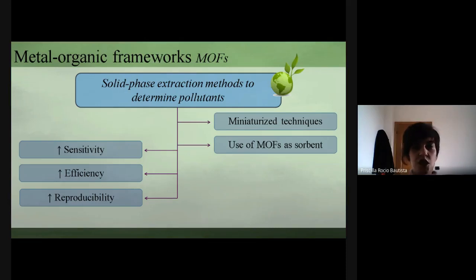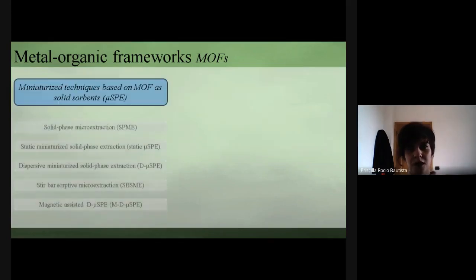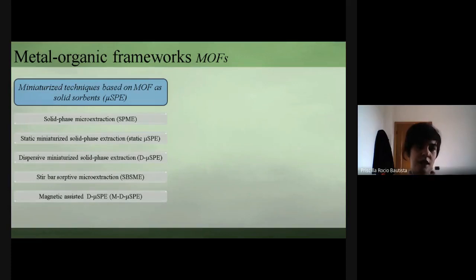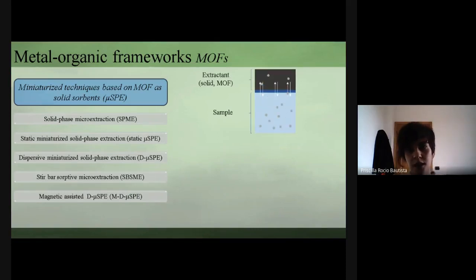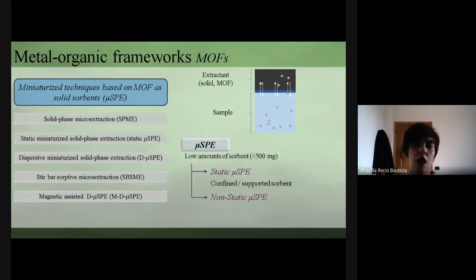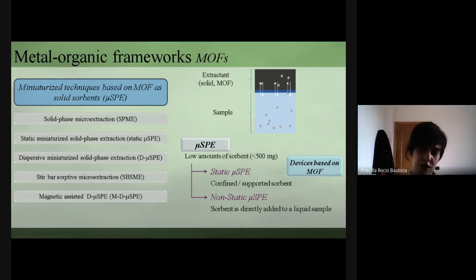Due to their characteristics, MOFs have been described as sorbents in solid phase extraction methods to determine pollutants in different matrices. The potential results are the increase of sensitivity, efficiency, and reproducibility of the overall procedure. In the literature are included several miniaturized techniques based on MOFs as solid sorbent. All of them imply the transfer of analyte between a liquid sample and a solid extractant through partition equilibria. The miniaturized solid phase extraction uses a low amount of extractant sorbent, always lower than 500 milligrams, and can be divided into two types: the static mode, where the MOF is confined or supported on a device, or non-static, where the MOF sorbent is directly added to the liquid sample. This presentation is focused on the devices based on MOFs and their use in static approaches.